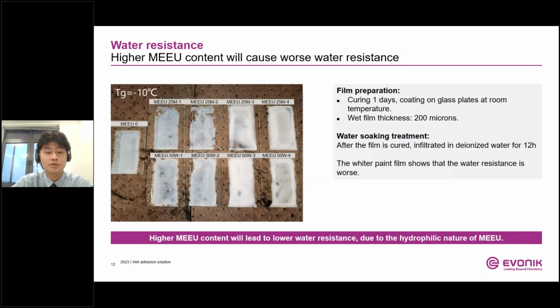And then for the pure film application section, after emulsion synthesis, we apply a 200 micrometer wet film to the glass plates and cure it for 24 hours at room temperature. To test the water resistance, we soak the cured film in water for another 12 hours and observe the whitening of the pure film. If it is whiter, it means that more water has entered the film, which shows the water resistance is poor. The film that has been immersed in water is shown in the left side picture.